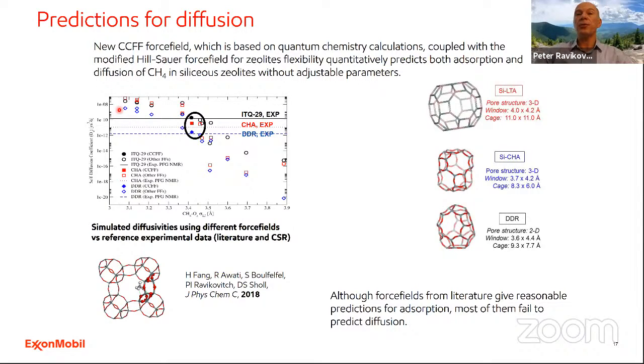What is plotted here is diffusivity predicted by molecular simulations using different force fields which were reported in the literature. Most of these force fields were reported to work pretty well for equilibrium adsorption of methane in silica zeolites. But when we apply these force fields to calculate diffusion, the results differ by many orders of magnitude. And when we use the force field which we developed based on first principle calculations, we actually get results which are in very good agreement with experimental measurements. This is a really interesting example showing that for certain properties like diffusion, if the force field is not accurate, the results could be very misleading.